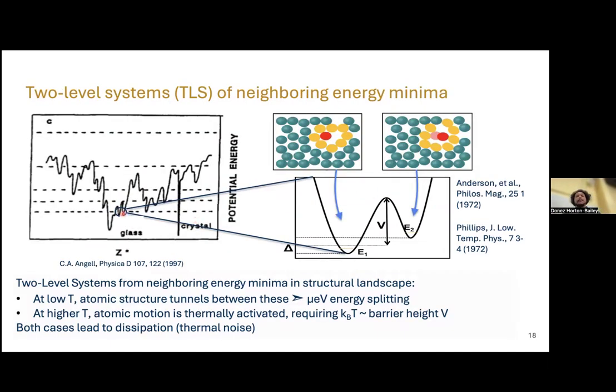And so what happens is we have several of these states that are really close to each other, and we have these two neighboring states called, I call them tunneling two-level systems. They're two-level systems because you have two energy levels, and at low temperatures, you're going to be able to tunnel between these two states. So despite the energy level being lower than the height of this potential barrier, you're actually able to tunnel between this. And in glasses, since we're talking about a large cluster of atoms, each of these states represents an entire group of atoms moving, not just one individual atom moving from place to place. So here we have two different configurations going back and forth.